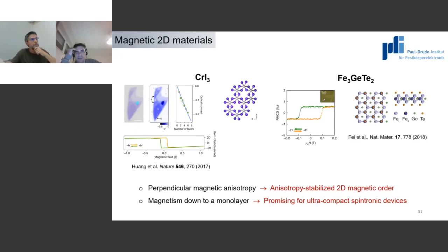That's correct. But I know from some works, we never try to really fit our SQUID curves considering, for instance, the Heisenberg model. One of the reasons in our case is that we have stacking faults, we have different phases. You can see that our SQUID curve does not go abruptly to zero, which would indicate a phase pure material, but we have probably many different phases there. But I know from another group growing more phase pure Fe3GeTe2, and they are also not able to fit to a perfect Ising model. I think things are more complicated than a perfect Ising model.